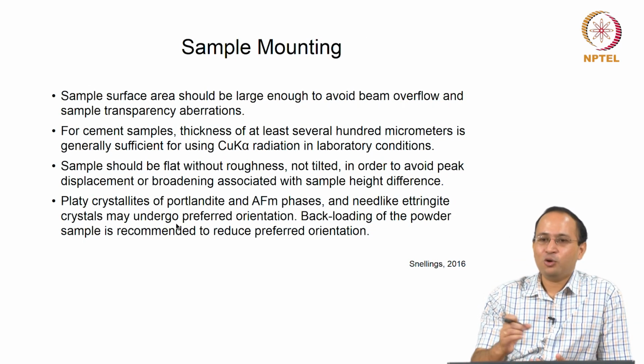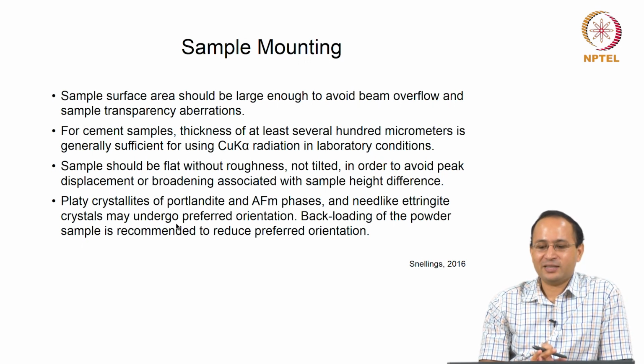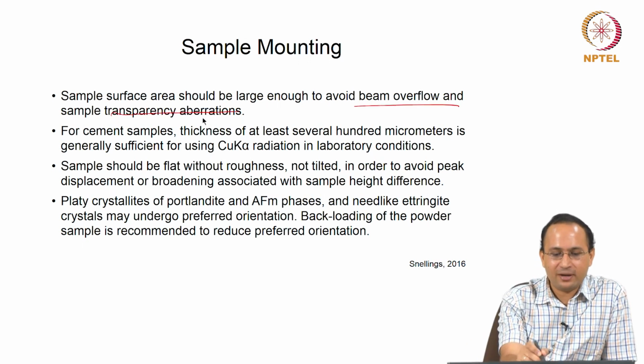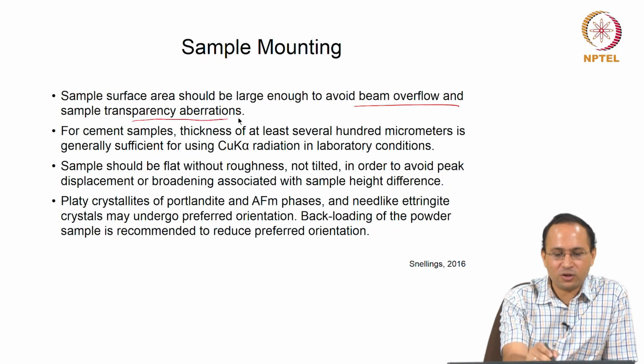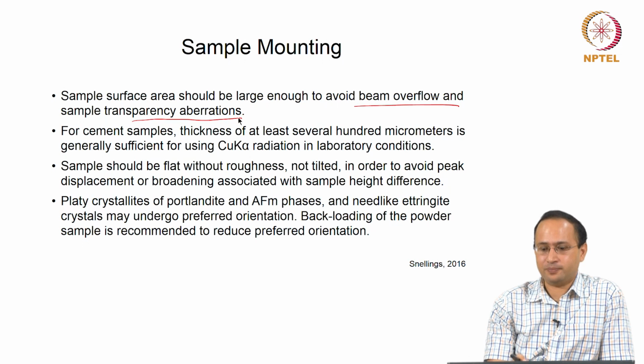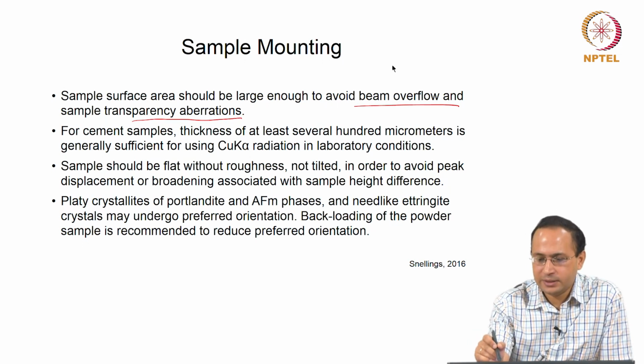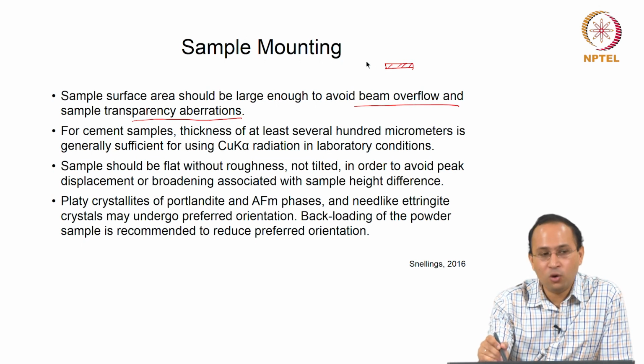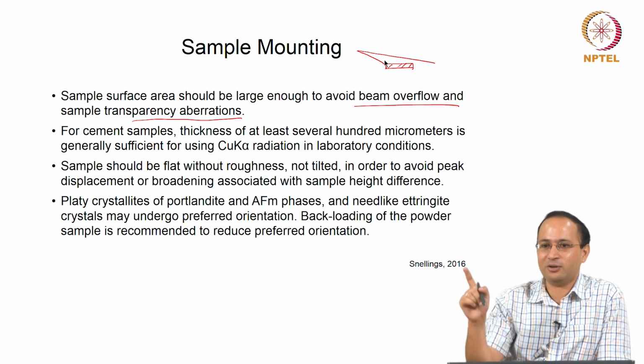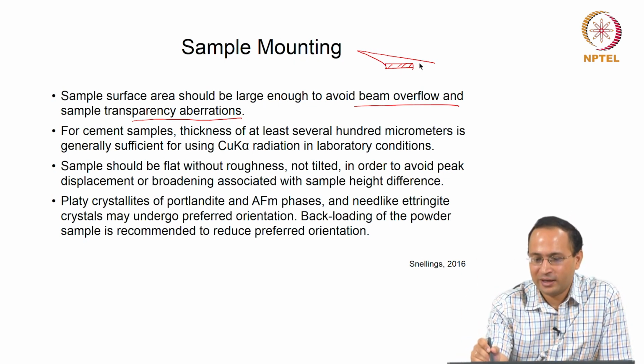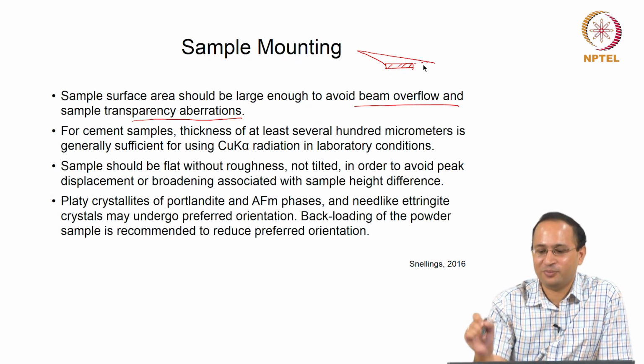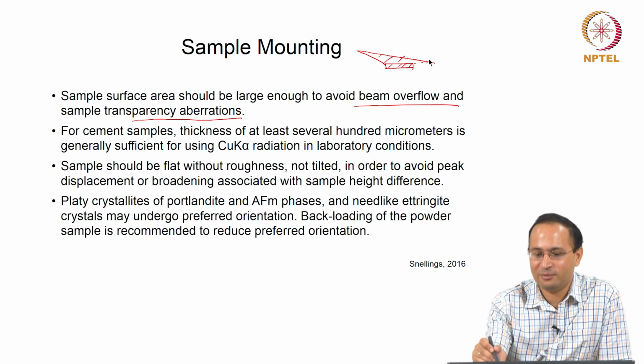So, now you have a sample, how do you mount it for X-ray diffraction? The sample surface area should be large enough to avoid beam overflow and sample transparency aberrations. You want to make sure you have enough thickness of the sample. It is easy to visualize: at lower angles, your beam will be like this. We are talking about theta, you are changing your theta to 2 theta. So, your sample should not be so small that there is a beam overflow. You have this beam at lower angles, and you see it changes like this.